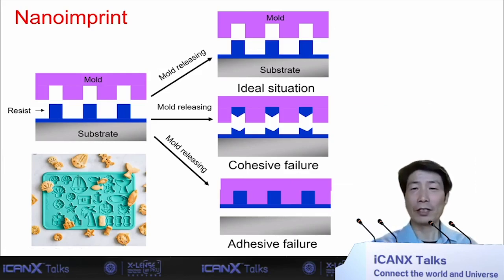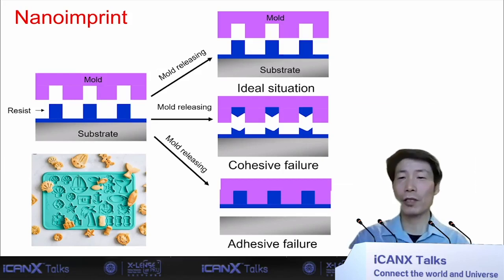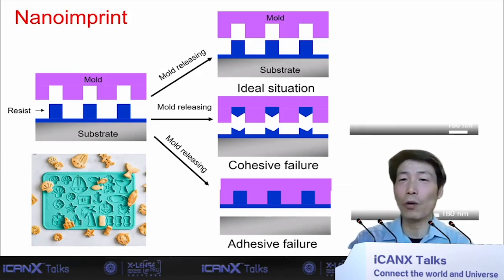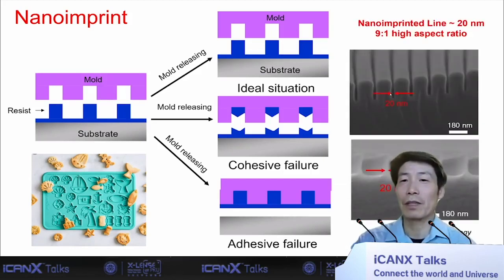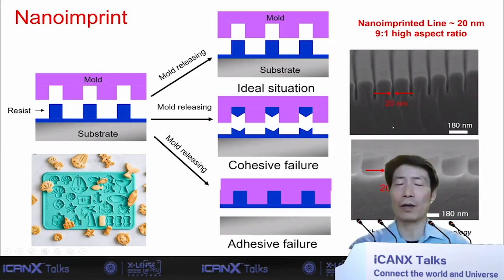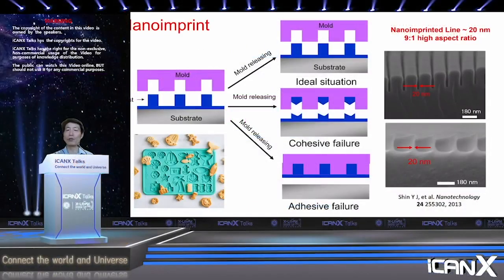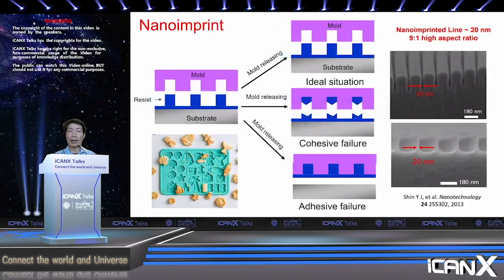Now, I'll just give you an example from my own laboratory. This is the work of a former student. You can see that he made a very special mold with only a 20 nanometer gap, almost 200 nanometers tall, by atomic layer deposition. And he used this mold to imprint into a specially designed polymeric film, because a typical polymer will not be able to stand this. And you can get a 9:1, very high aspect ratio. So we can actually make those types of structures.